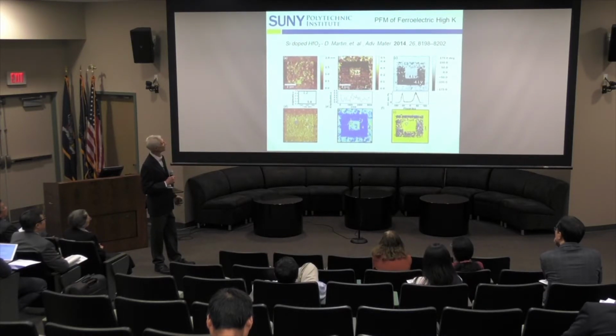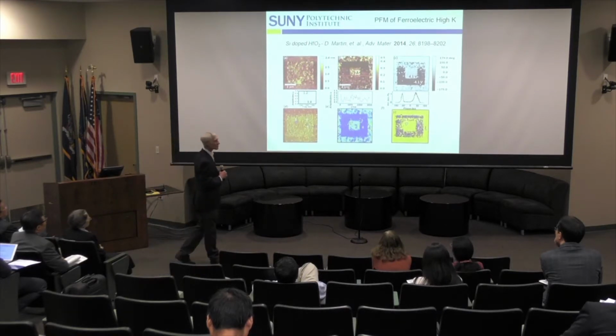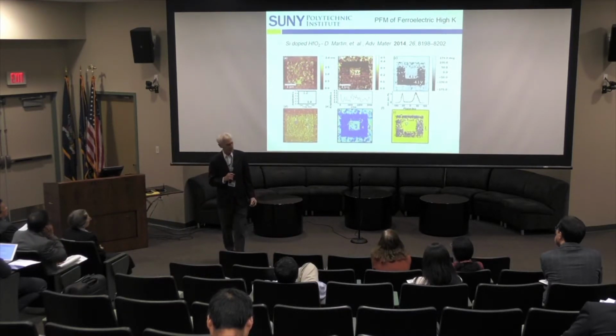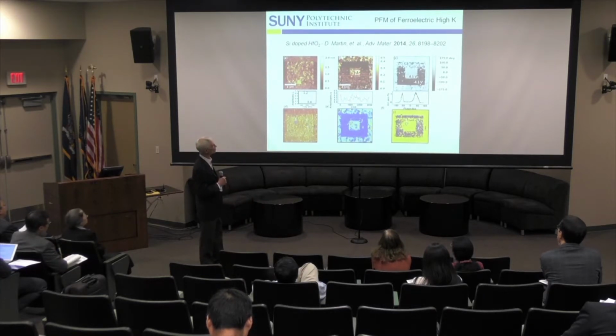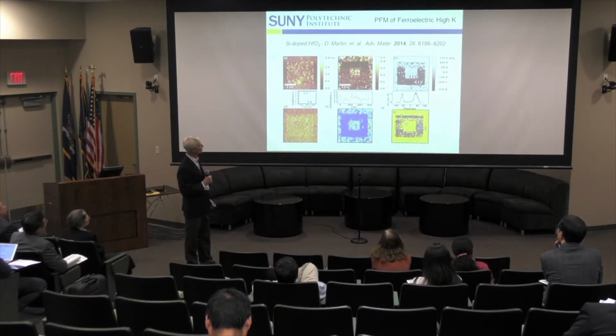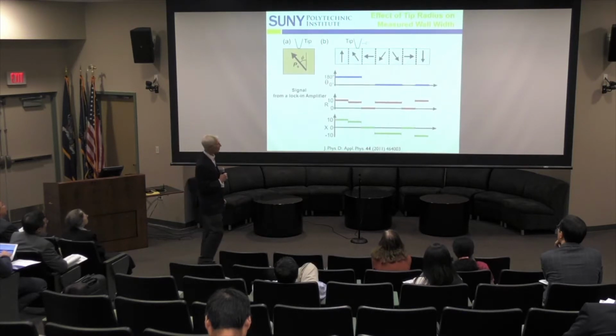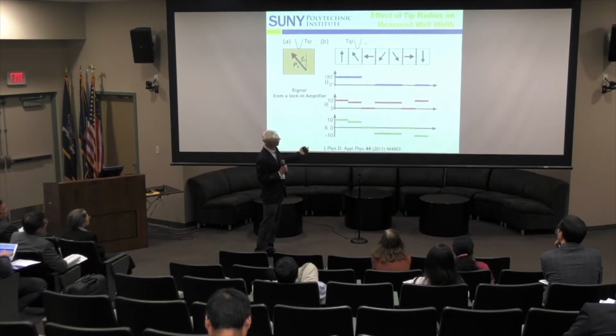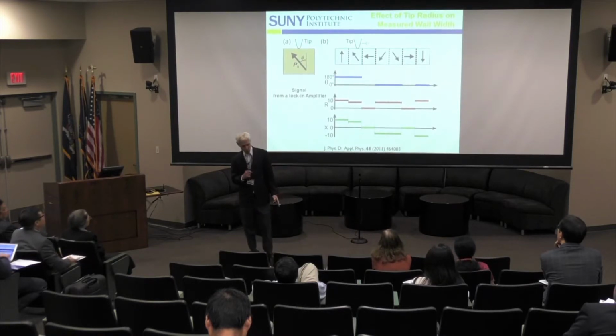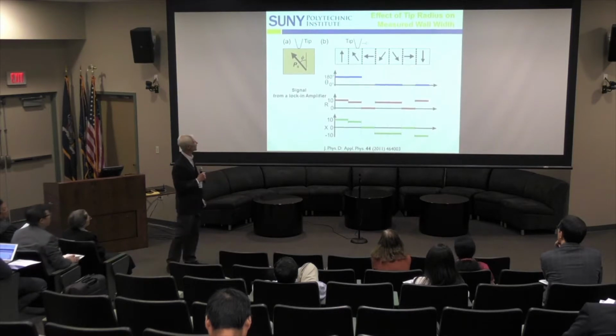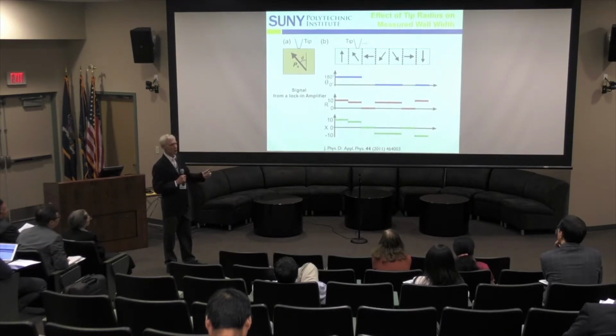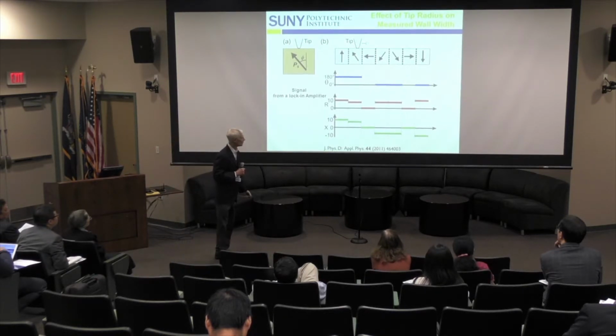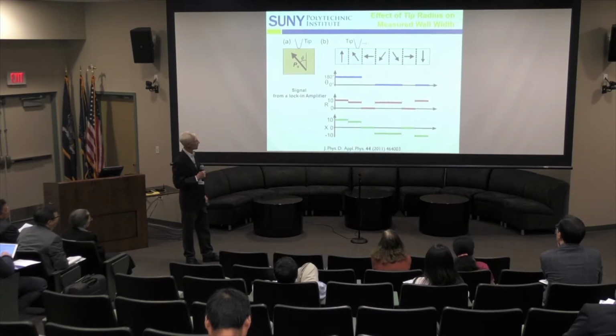Here's another publication for silicon-doped hafnium oxide. So that's even more exciting, since the hafnium zirconium oxide is a material of great interest to the research team I was talking about. And you can see that they can map out where the ferroelectric material is here and so forth. There's even a paper that talks about using a lock-in amplifier to determine the exact direction of the polarization. And so the purpose of showing this overhead is that the polarization isn't always up or down. It can be to the side or at some angle. And with a little bit of careful experimental work, as talked about in this paper here, you can determine something about the angle of the polarization.